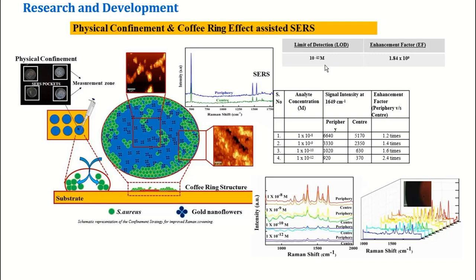And now if you just squeeze this radial direction so that the center and periphery merge, then you can get the signal from everywhere. So that was the idea, and it has been published. And once we do this squeezing of the structure in the micro scale, we can get this sensitivity very high, and wherever you hit with the laser, you get the signal. And that was the importance of this work, and it was published in 2018.